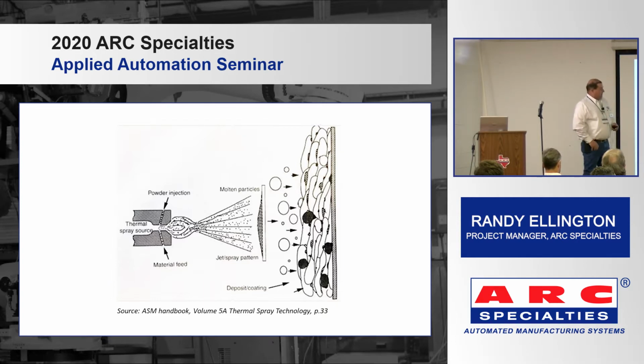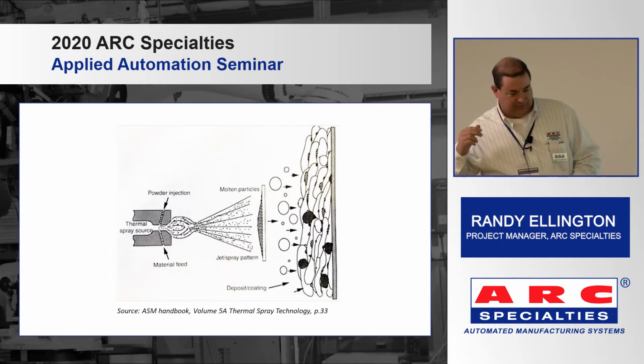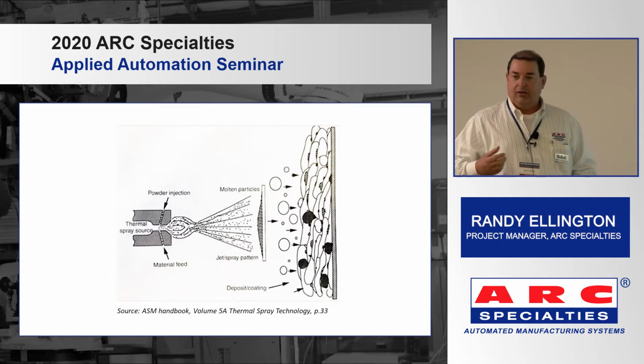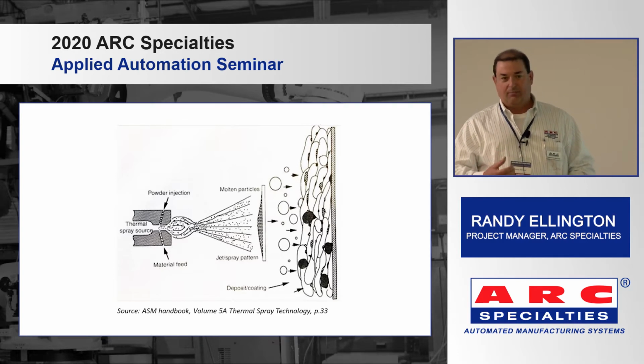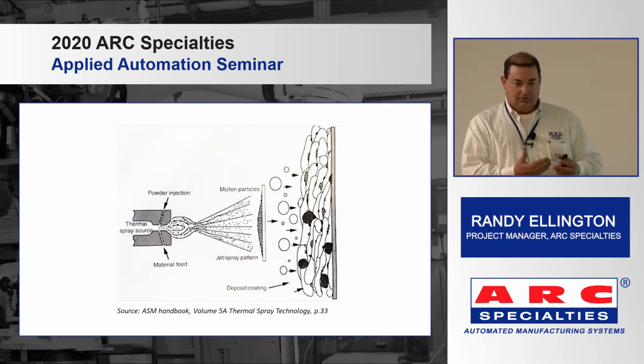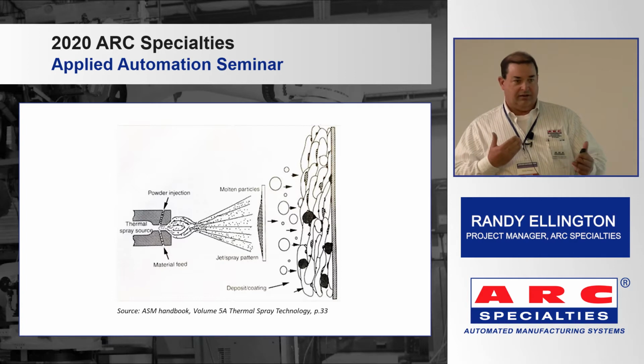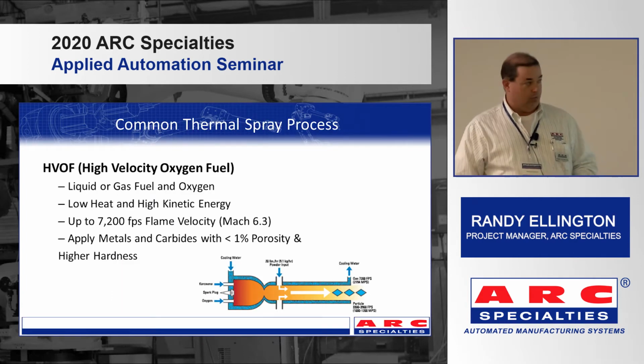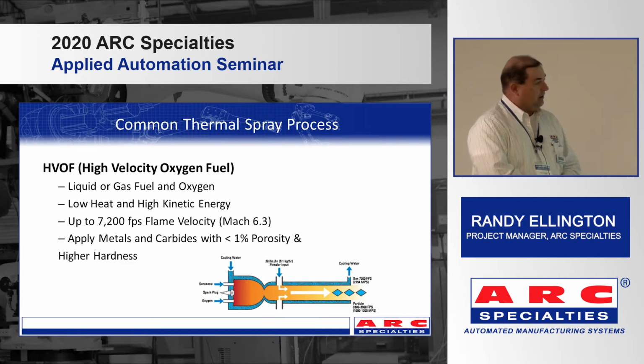The other end of that spectrum, if it's in the flame too long, you overheat and you oxidize and you ruin the properties of the material that you're putting down. So the actual spray distance is very critical, and that's one of the reasons it's good to automate.